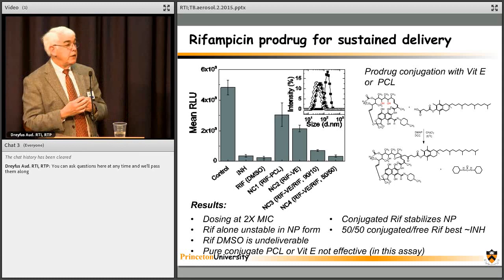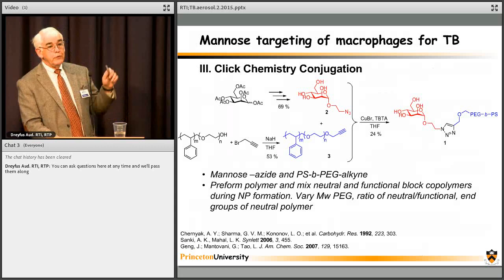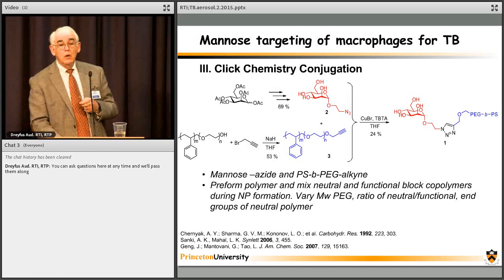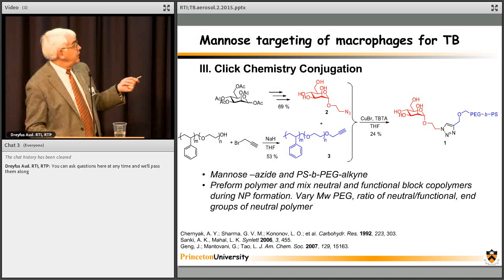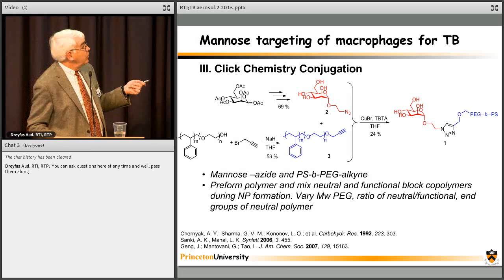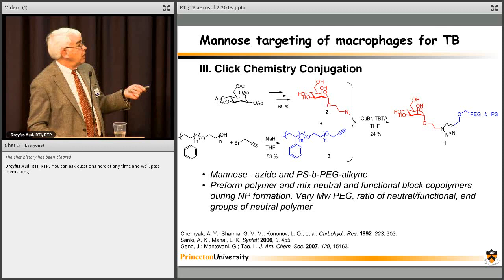So now let's look at targeting. That's the drug delivery part of it. I said the macrophages have mannose receptors, looking for mannose sites on the mycobacteria to engulf. So what we do is we take, in this case, a polystyrene PEG, we put a click alkyne on that, we make the mannose here, we put an azide on that, you then do click chemistry, and now we have the block copolymer PEG with our targeting mannose on it.